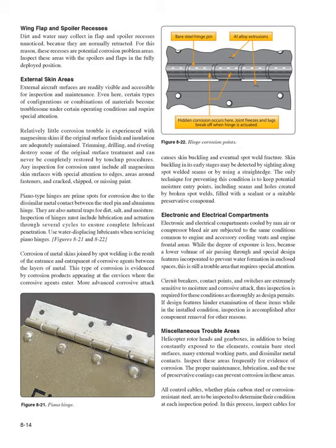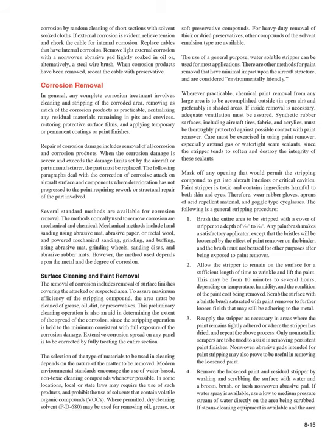All control cables, whether plain carbon steel or corrosion-resistant steel, are to be inspected to determine their condition at each inspection period. In this process, inspect cables for corrosion by random cleaning of short sections with solvent-soaked cloths. If external corrosion is evident, relieve tension and check the cable for internal corrosion. Replace cables that have internal corrosion. Remove light external corrosion with a non-woven abrasive pad lightly soaked in oil or, alternatively, a steel wire brush. When corrosion products have been removed, recoat the cable with preservative.